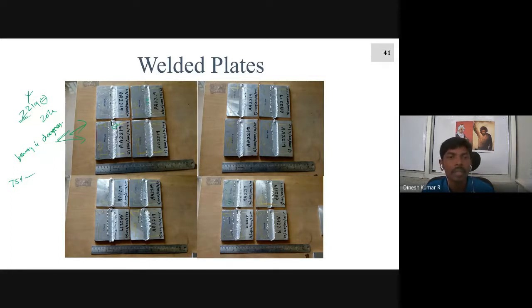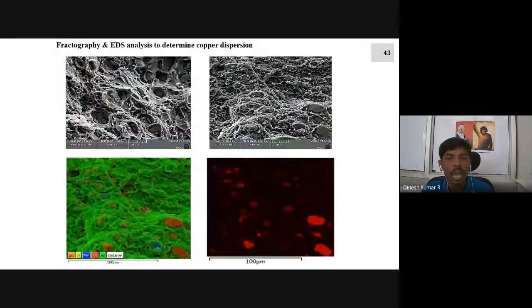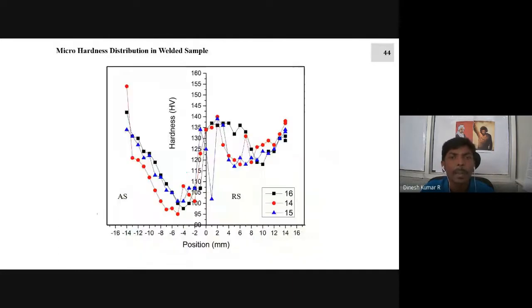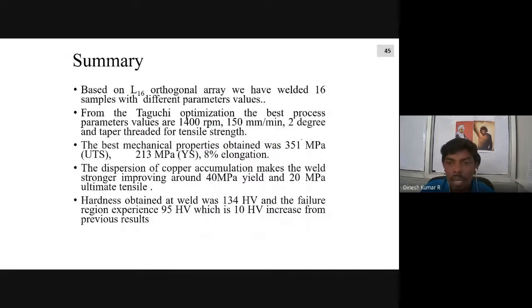But luckily, when we did all the characterization testing, it was found that the crater at the beginning and the end, which was around 10 mm, got completely reduced, and fine precipitates and fine segregation were there everywhere, and the copper precipitates were completely done. Finally we got around 40 MPa increase in yield strength, 20 MPa increase in yield strength and 40 MPa in tensile strength, and the efficiency was around 88%, where earlier it was only 75%. So by optimizing this process, we were able to achieve almost 88% efficiency, which was our required target for that welding process.